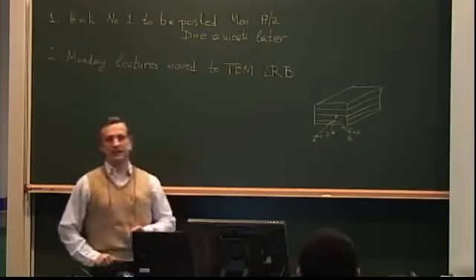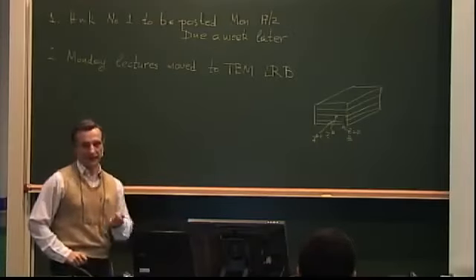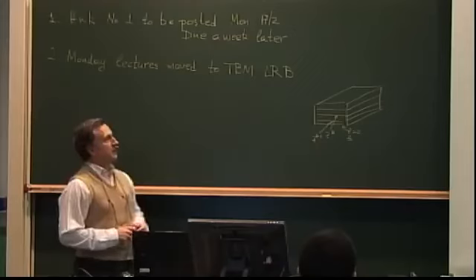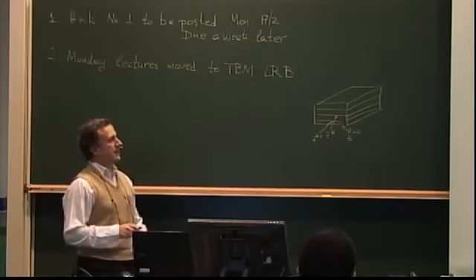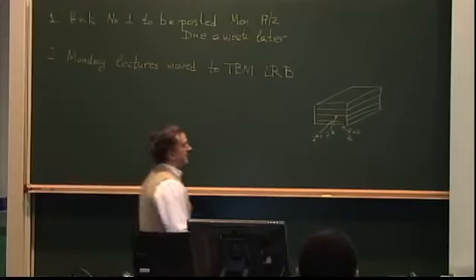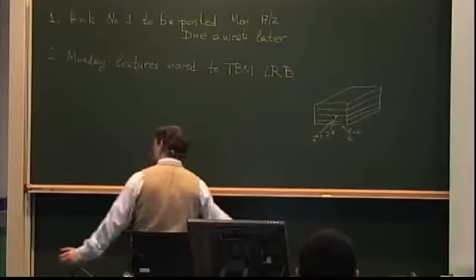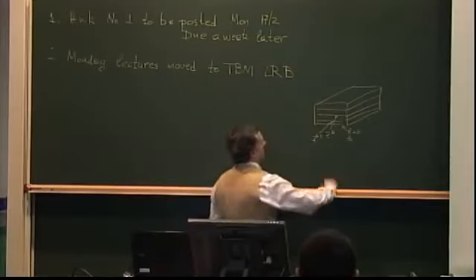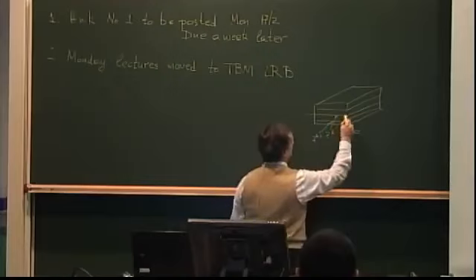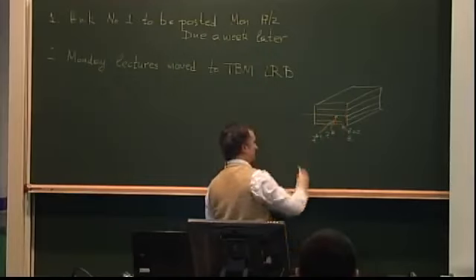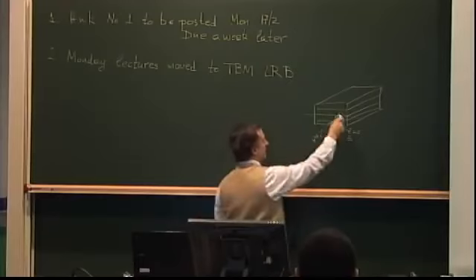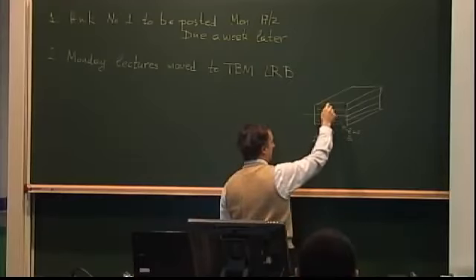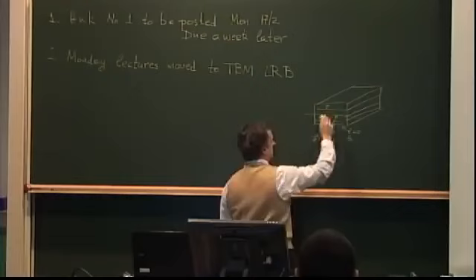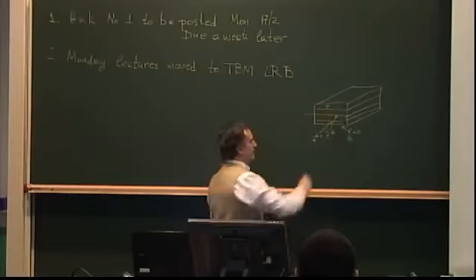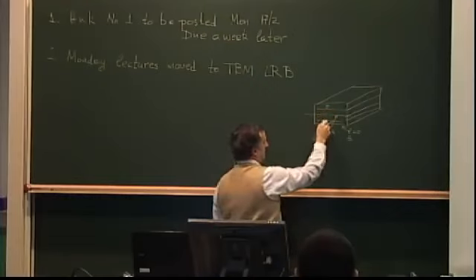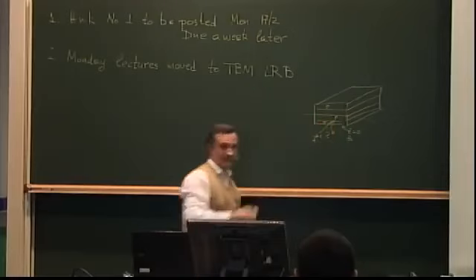Two important characteristics of certain classes of laminates. If I have a symmetric laminate, then the B matrix is 0. Symmetric means that with respect to my mid-plane, which in this case with my 4-ply laminate is just 2 layers above and 2 layers below, a certain ply which has an orientation theta will have a corresponding one at exactly the same mirror image location, which has exactly the same orientation.